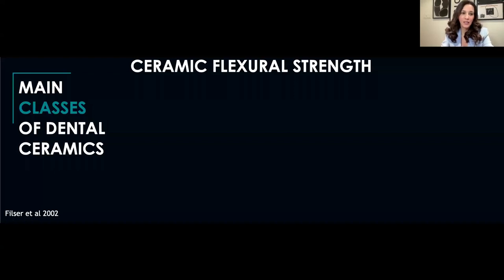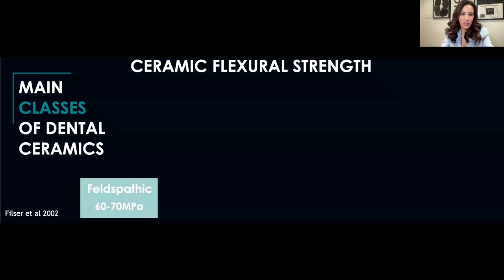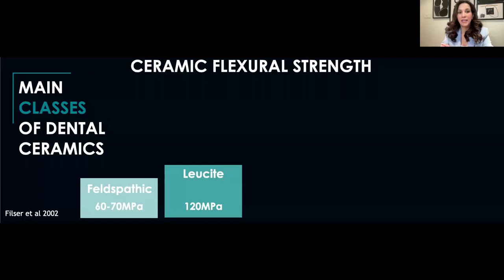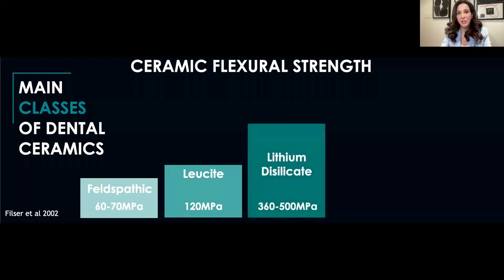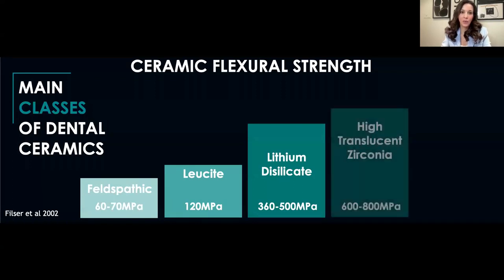So if you look at a graph that demonstrates ceramic flexural strength, you can appreciate that the weakest material is in fact your feldspathic porcelains, and the strength there is between 60 to 70 megapascals. As we move along with the various materials that we have available, we get glass ceramics that are infused with a material like leucite, for example. So that would be your IPS Empress, which gets a little bit stronger at 120 megapascals. Even stronger is lithium disilicate, which a lot of us are familiar with, otherwise known as e.max. It has a flexural strength of anywhere between 360 to 500 megapascals, depending on how it's bonded into place.